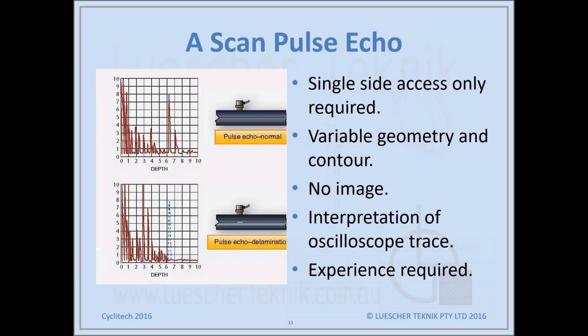Here we have another example of an A-scan pulse echo. Access is only required from one side, so it's a single transducer. In this case we're looking at a flat panel, but it's suitable for a variety of geometrical shapes and contours. There is no typical image like you get with an X-ray or a B-scan or a C-scan. So the interpretation is directly off the oscilloscope trace, which, as discussed, requires experience.